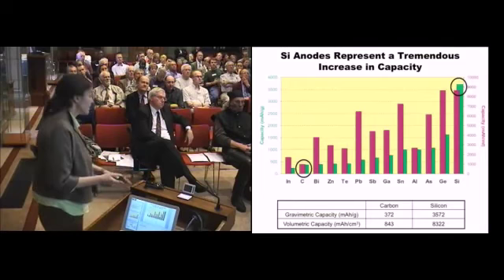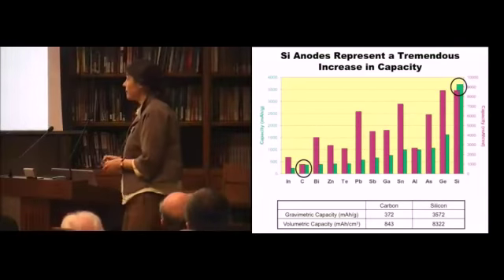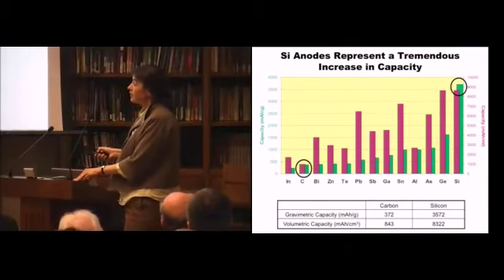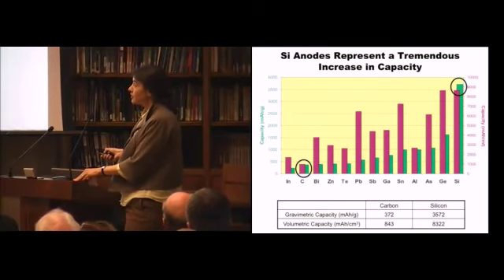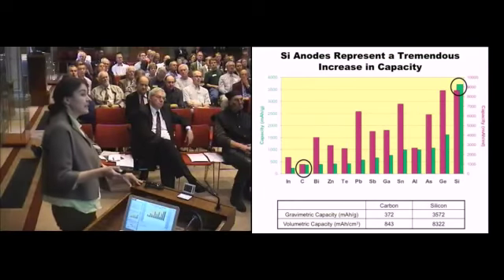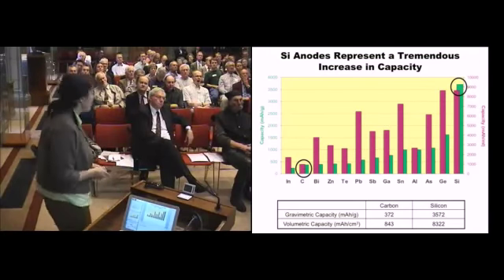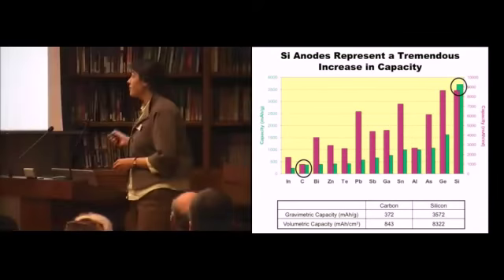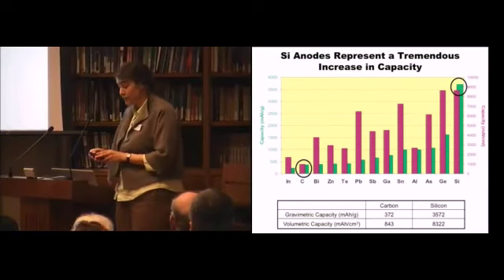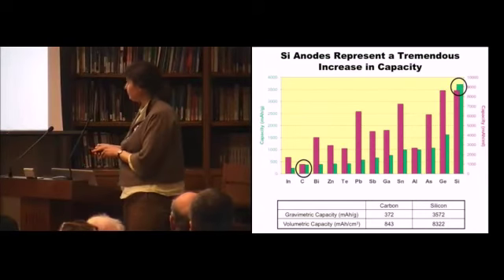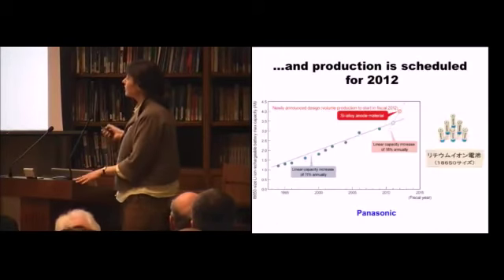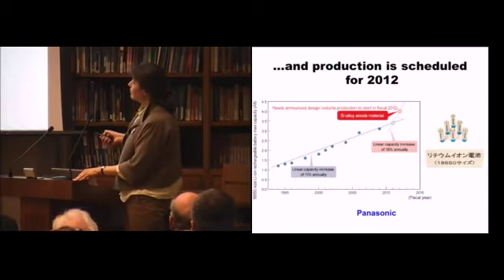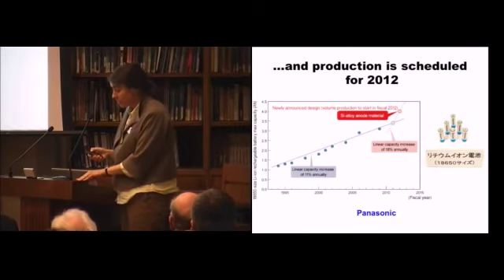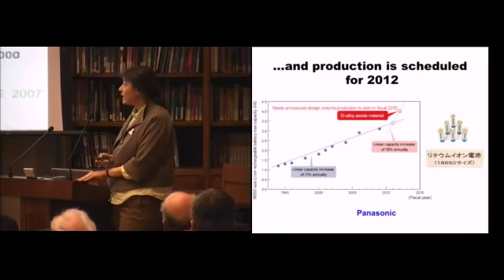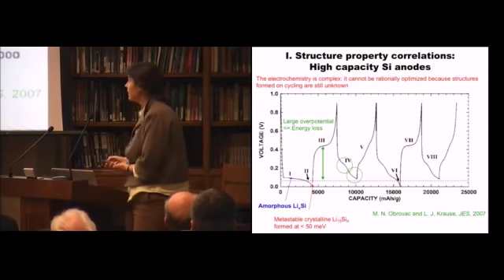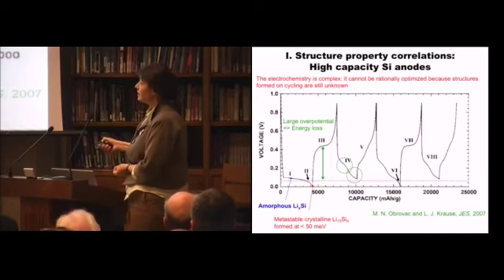Silicon is a replacement for graphite. Here's graphite with about 372 milliamp hours per gram, and silicon has a tremendous increase in capacity of more than 10 times, both in terms of gravimetric capacity and volumetric capacity. Panasonic has just announced, in one of these publicity things, that they're going to produce this material in 2012. Yet actually no one knows how it works. Here's the typical voltage profile.